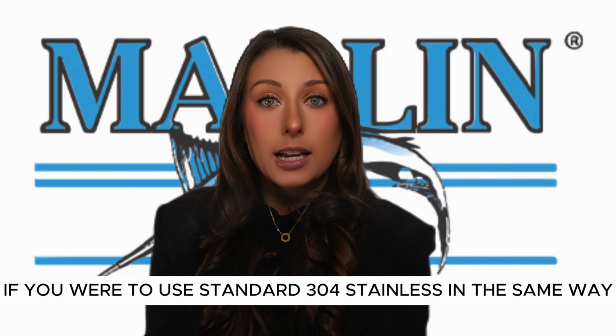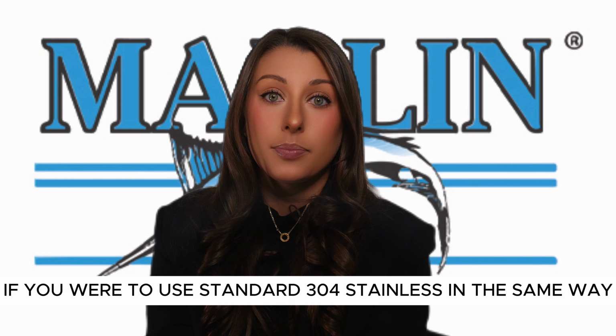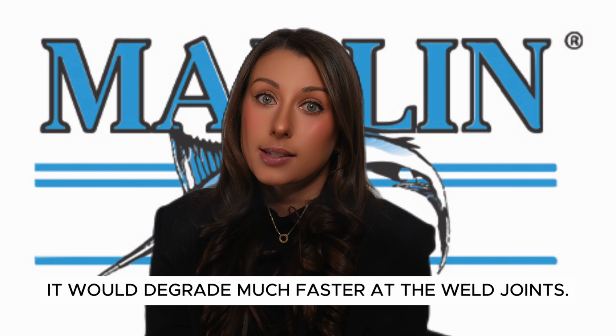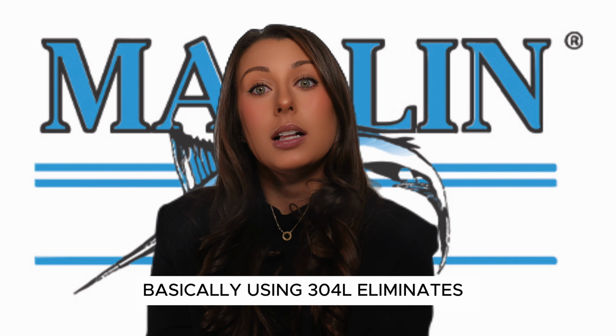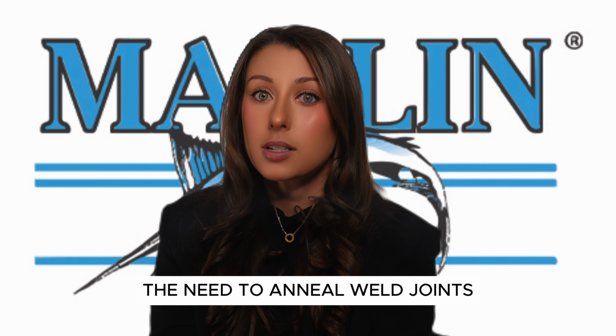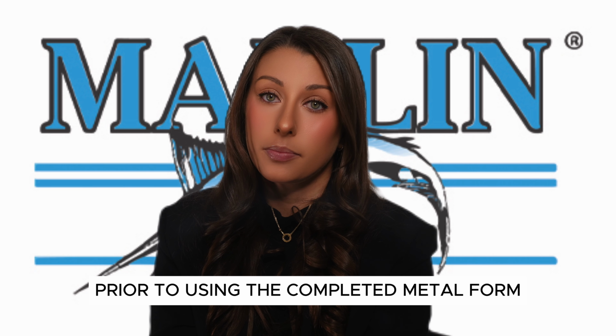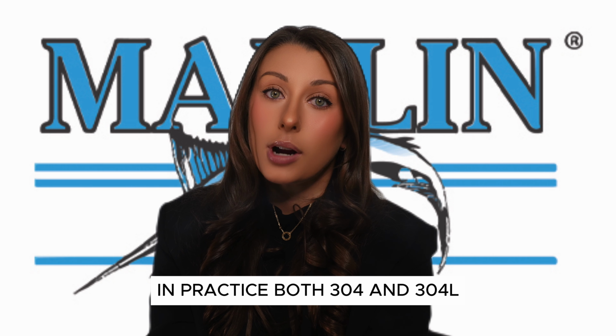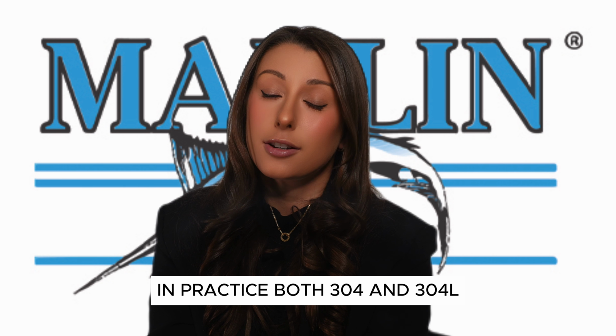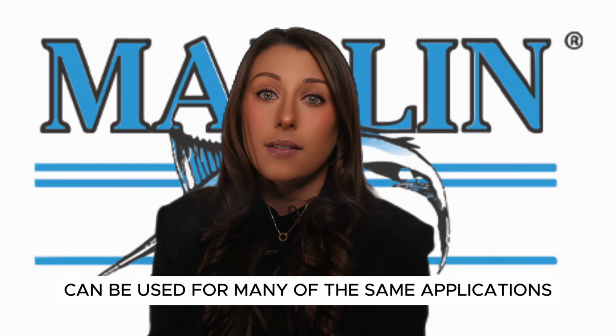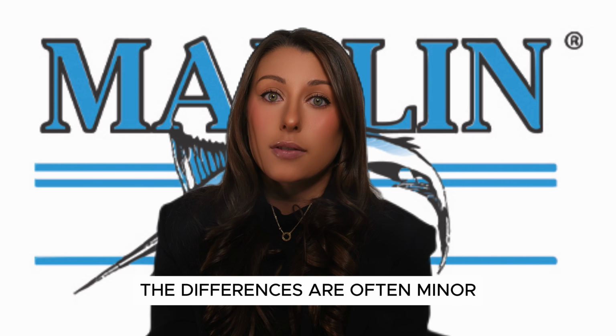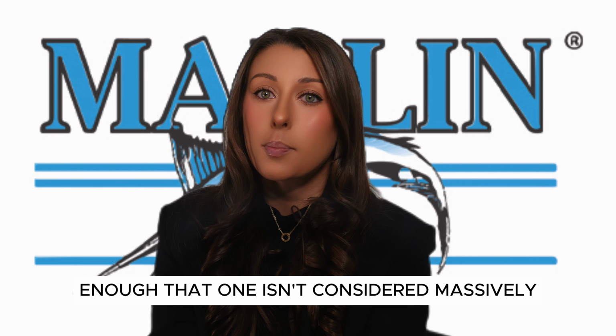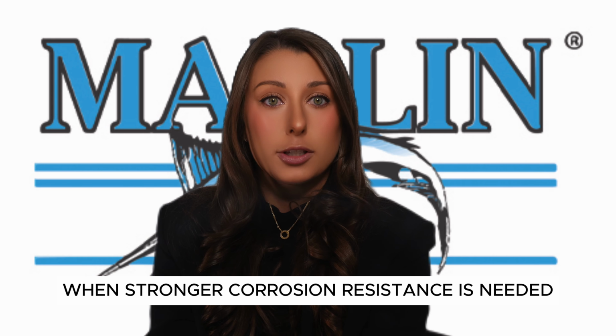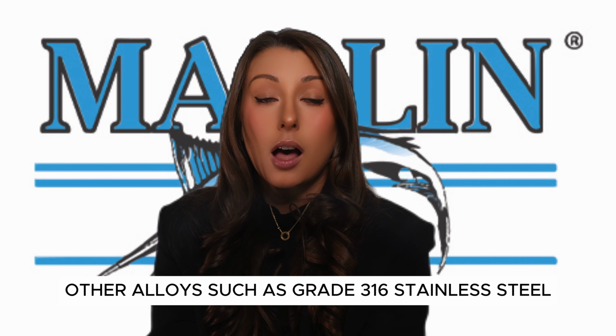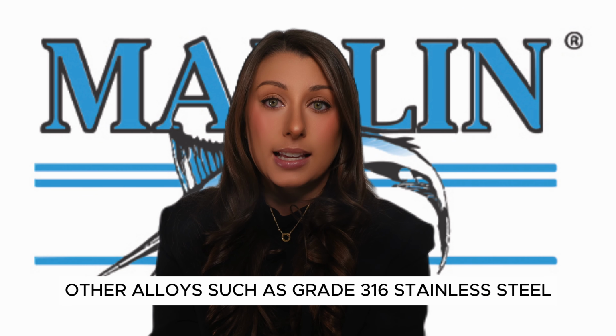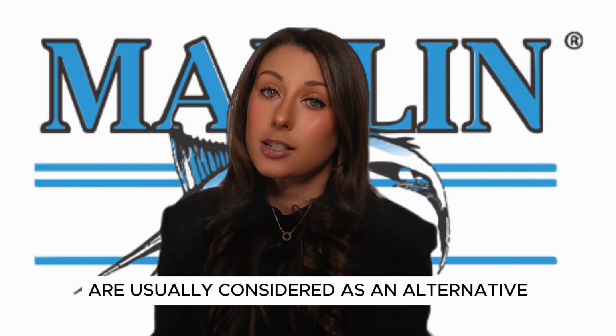If you were to use standard 304 stainless in the same way, it would degrade much faster at the weld joints. Basically, using 304L eliminates the need to anneal weld joints prior to using the completed metal form, saving time and effort. In practice, both 304 and 304L can be used for many of the same applications. The differences are often minor enough that one isn't considered massively more useful over the other. When stronger corrosion resistance is needed, other alloys, such as grade 316 stainless steel, are usually considered as an alternative.